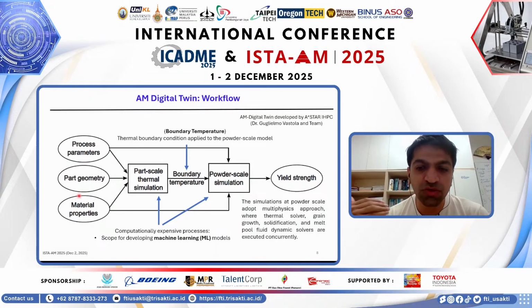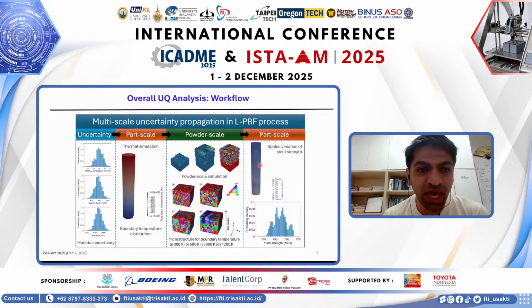So we want to use machine learning tools to increase the speed of this simulation by as much as 1,000 to 10,000 times more efficiency, with a small compromise in the accuracy of 2 to 3%. So we will of course have some compromise to make in machine learning or reduced order models for additive manufacturing, but we have ensured that the accuracy drop is only 2 to 3%. So that is far less compared to the improvement you get in efficiency by 10^3 to 10^4 times. So this is the entire framework that we have been working on with our collaborators in IHPC.